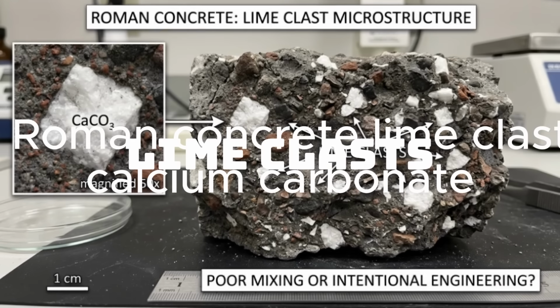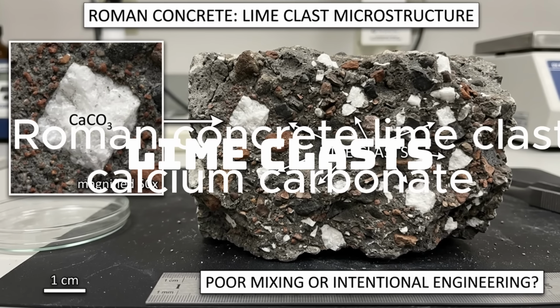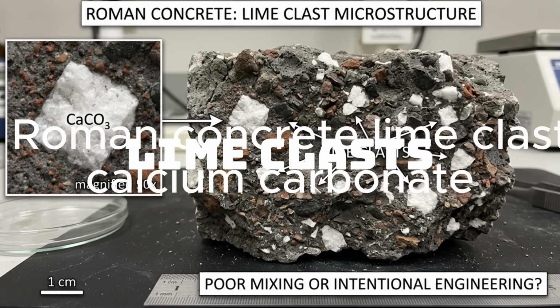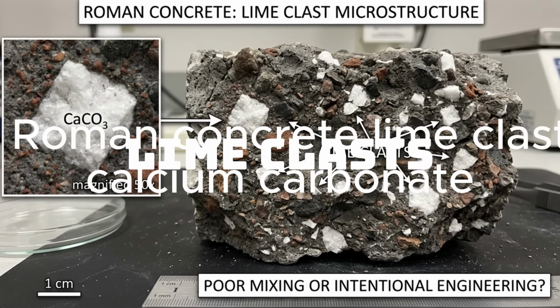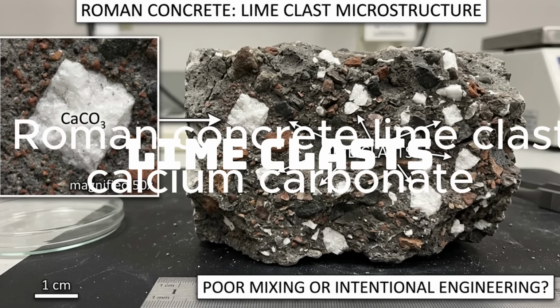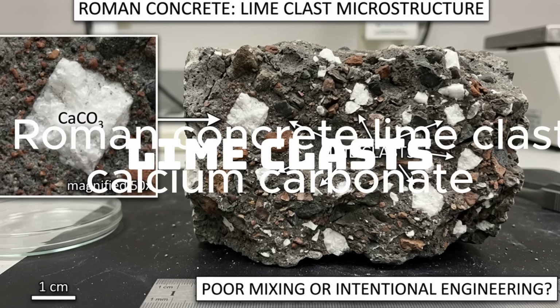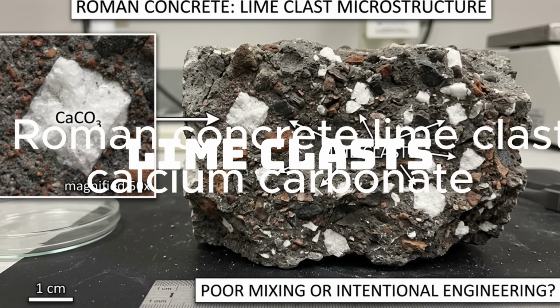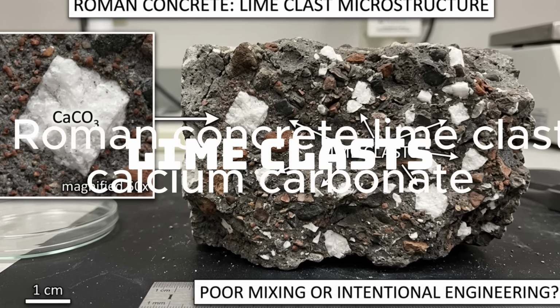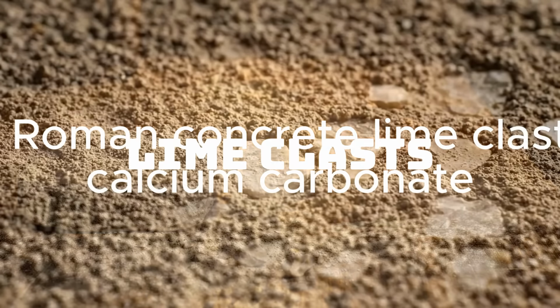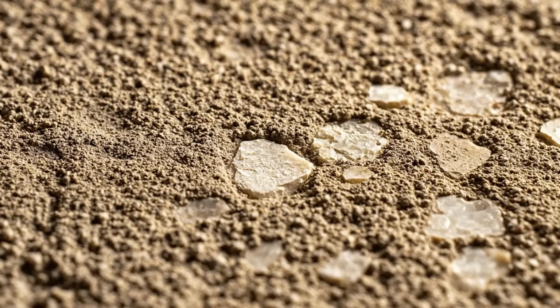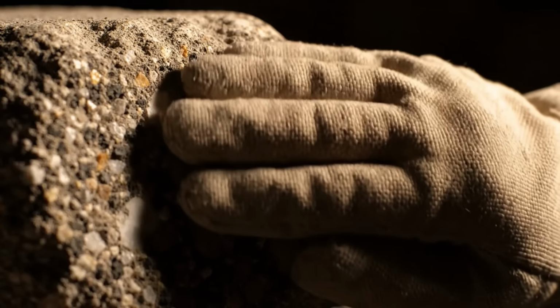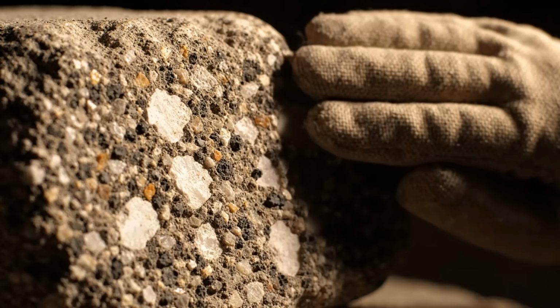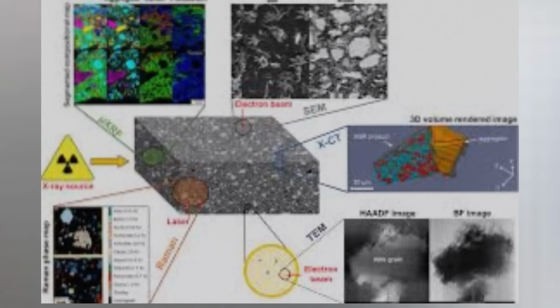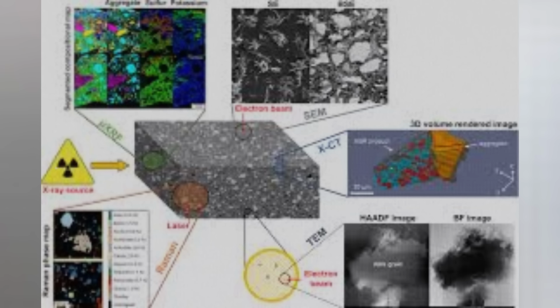For decades, archaeologists had noticed small white inclusions scattered through Roman concrete samples. Millimeter-scale chunks of bright calcium carbonate they called lime clasts. The standard interpretation was that Roman workers had simply mixed concrete poorly. Masic refused to accept that. The Romans had perfected this material across centuries. They would not have tolerated sloppy mixing on the most important construction projects of the empire.